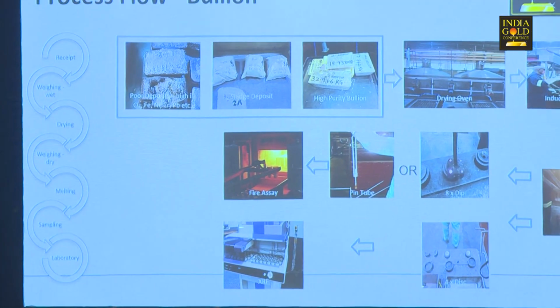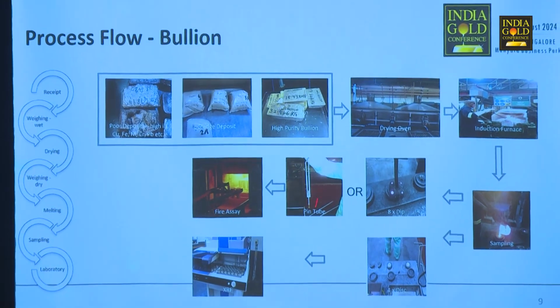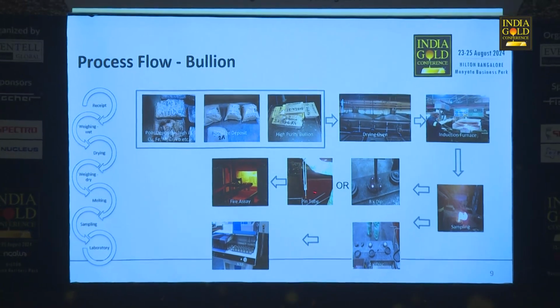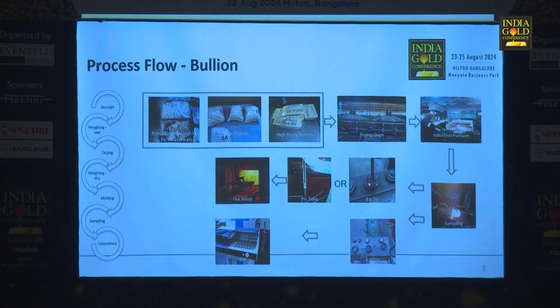But if a deposit gets to be larger in size, there's a method that we do use to make sure that we increase the random sampling of the dips and the discs that we do take. We also have an ability to take pin tube and drills, and then we use fire assay, and then we use the XRF. We've got 2 XRFs that we use in comparison to make sure that we can understand the chemical makeup of the material, plus to get an estimate of what the precious metal is. But we use fire assay as our gold standard.